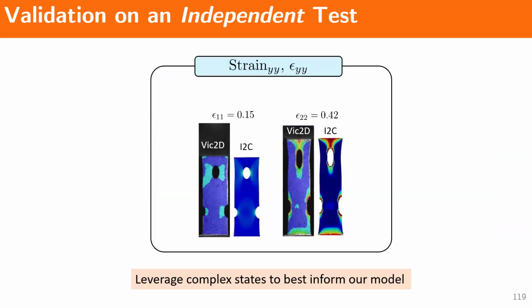Okay, but what I want to particularly highlight here is that experimental data, such as VIC-2D data that we analyze with I2C, tend to be quite sensitive, as I was talking about earlier. Near boundaries and near holes, the displacement field tends to be really sensitive to the subset size or the regularization parameters that you use. But because of the nature of our method, we're still able to recover the behavior at these complex states. And so this allows us to potentially leverage complex states to inform our model recovery of these materials.